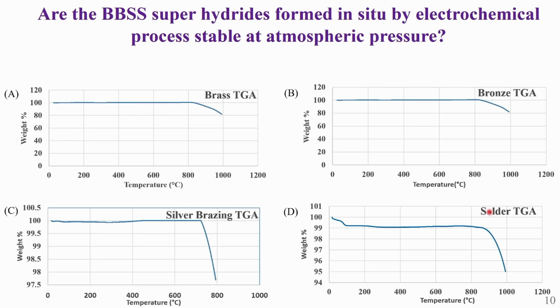To check for any possible stable superhydride phases formed due to electrolysis in the electrode, we conducted thermogravimetric analysis on the post-electrolysis electrode sample. From these results, we can observe that at around 900 degrees centigrade, the weight percent drops rapidly. This can be attributed to the decomposition of any potassium carbonate present on the electrode sample, as potassium carbonate decomposes at around 900 degrees centigrade in nitrogen atmosphere. This leads to the conclusion that there are no stable superhydride phases present at atmospheric pressure in the electrode sample